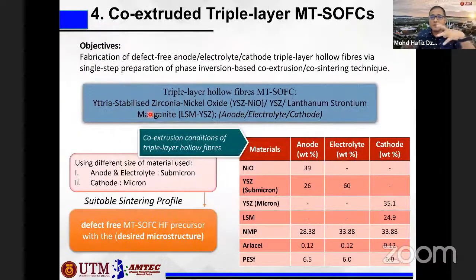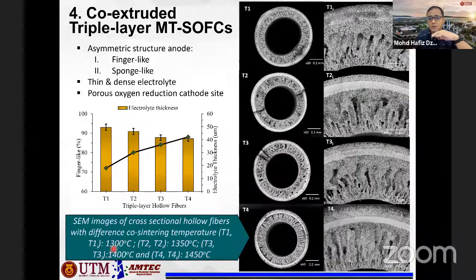We also tried to fabricate a triple layer hollow fiber membrane, but this one we use for higher temperature. We use yttria-stabilized zirconia, or YSZ, as the electrolyte. We fix everything and vary the sintering temperature from 1300 up to 1450. T1 is 1300, T2 is 1350, T3 is 1400, and T4 is 1450. You can see that the structure is almost the same, but in terms of densification, it becomes denser at high temperature. The mechanical strength also increases, and the thickness shrinks because at high temperature the grains become closer and shrink toward each other.